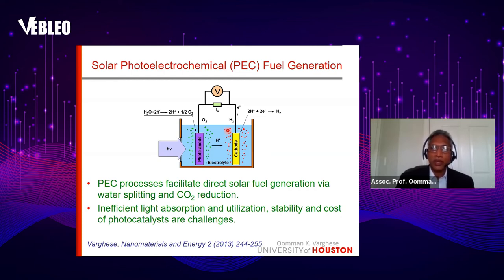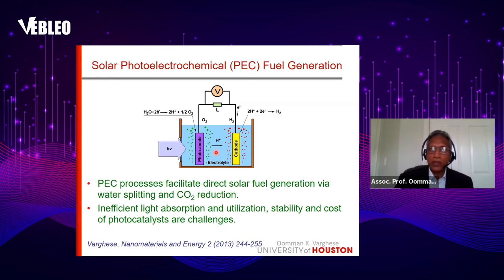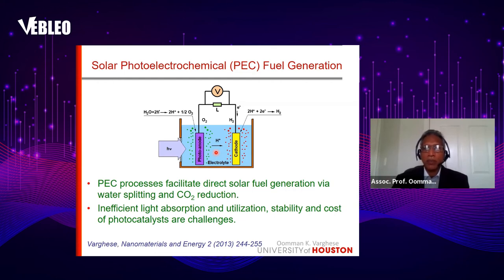For example, if we use water at the anode, the water is oxidized and we get oxygen, and at the cathode it is reduced to form hydrogen. The oxygen and hydrogen are formed in two separate regions — especially separated in this process. The efficiency in theory is very close to solar cell efficiency, in excess of 30%, but because of inherent losses in the photoelectrochemical process compared to the solar cell, the practical efficiency can go to around 16–18%. However, there have been many challenges in the material. Materials that are efficient are not stable — for example, gallium phosphide and gallium arsenide-based materials are very efficient but not stable in liquid electrolyte environments and are also costly. Other materials that are cheap either don't absorb light well or have stability issues. So the technology has not been commercialized.